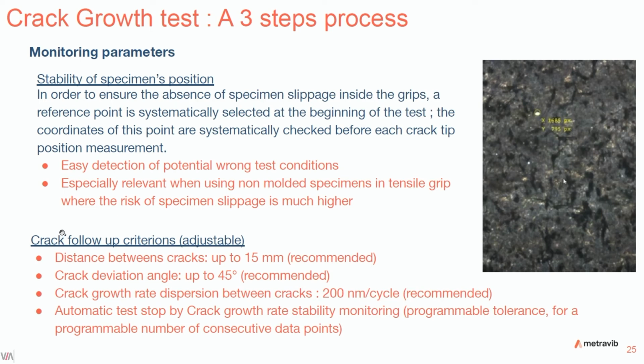What about crack follow-up criteria? All criteria are, of course, adjustable. The distance between cracks has to be up to 15 millimeters. The crack deviation angle is up to 45 degrees. And the crack growth rate dispersion between all the cracks on the same specimen should be about 200 nanometers per cycle. This is just a recommendation. The automatic test is stopped by crack growth rate stability monitoring, with a programmable tolerance for a programmable number of consecutive data points.